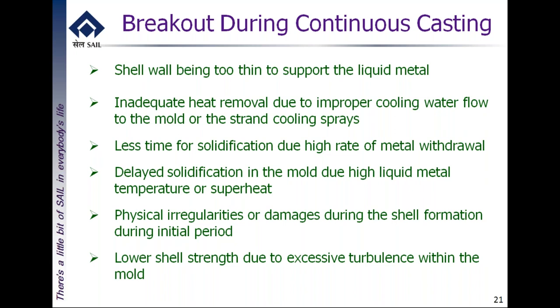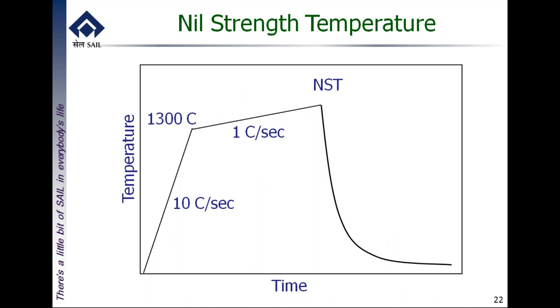For continuous casting, the zero ductility temperature test is performed using a simple tensile test at temperatures near melting. A very low tensile force of about 2 MPa is applied, and the sample is heated slowly — the material loses its ability to support stress and the sample breaks, giving the zero ductility temperature. This temperature must lie within a defined range inside the mold; if outside, unsuccessful casting and breakout will result.